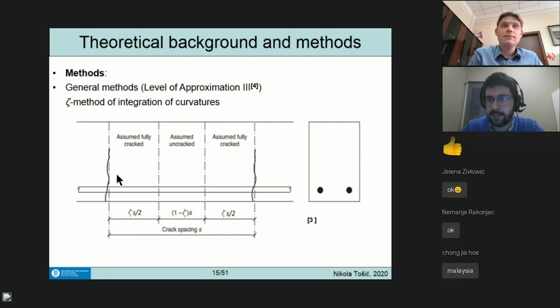So what this does is discretization of the concrete into discrete lengths that are assumed uncracked and fully cracked. Basically, in reality, between two cracks, you have some tension stiffening, which is the contribution of concrete between the cracks to tension, because not everything is fully cracked. But we cannot do it precisely for each point. So what we say is, on average, we're somewhere in between. So how do we get to this average? By saying that some parts are assumed fully cracked and the remaining part is assumed uncracked. And then when we average these together, we are somewhere in the middle or closer to one or the other.